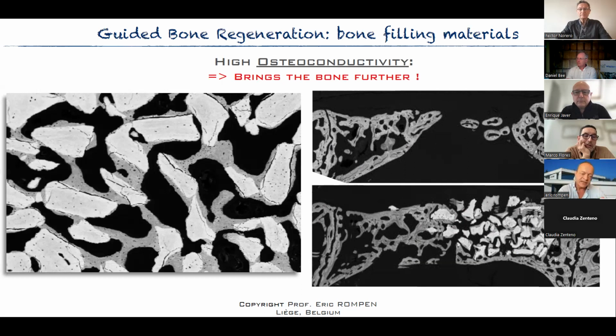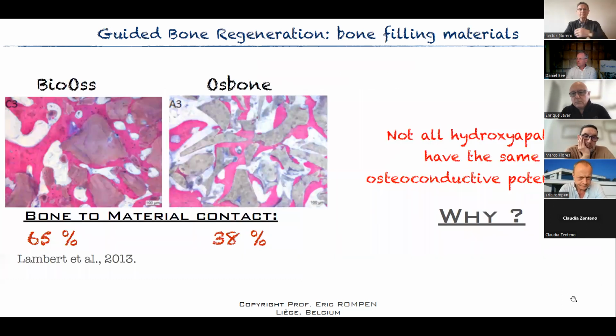The other advantage is that it will bring the bone further away. And you can see with this Bio-Oss here on rabbits, that when you place a nicely osteoconductive material, the newly formed bone can close the gap, whereas without any material, you cannot close the gap. It's impossible.